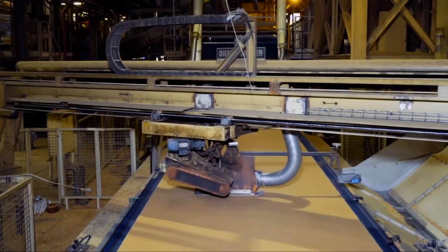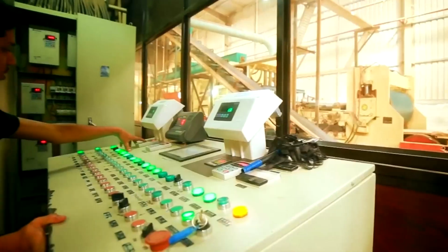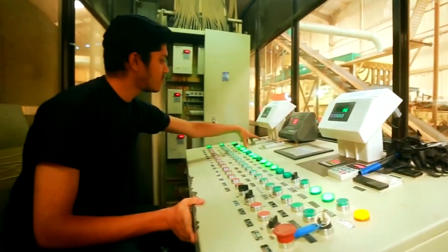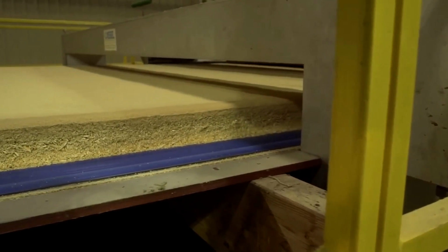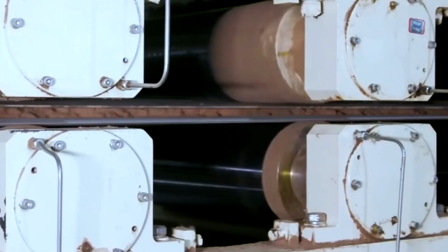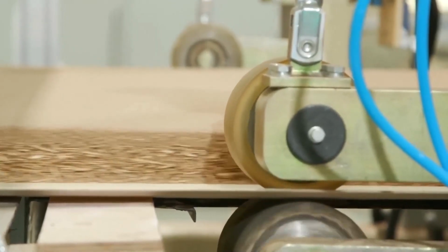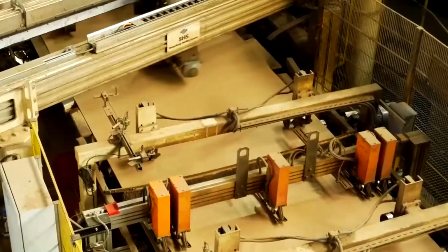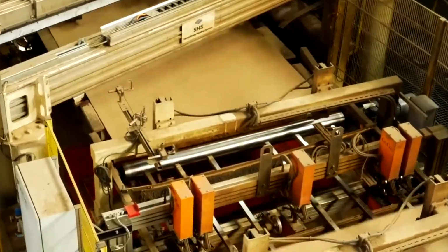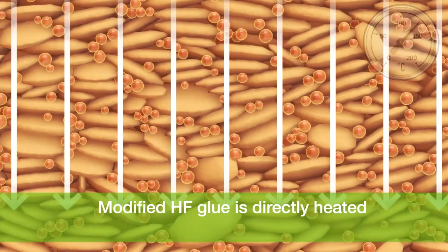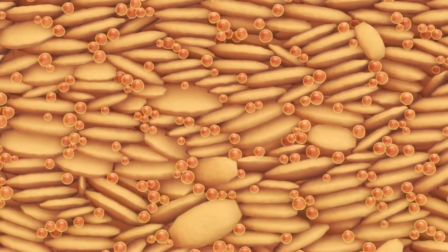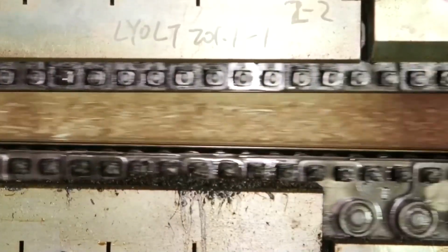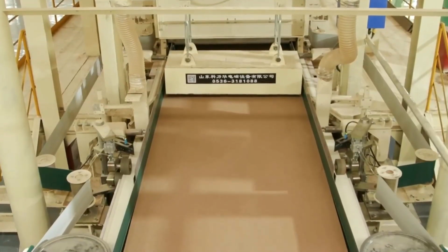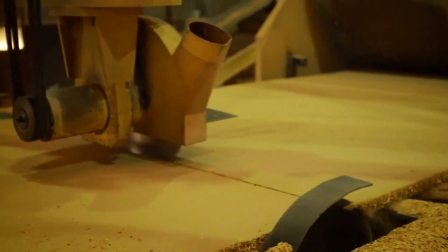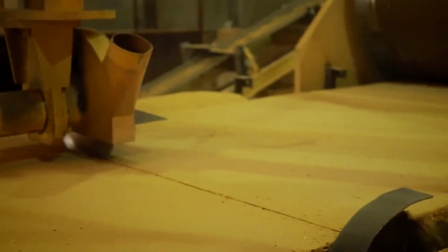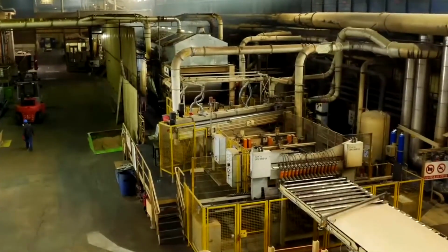Temperatures soar to between 280 and 430 degrees Fahrenheit, while pressure climbs as high as 600 pounds per square inch. For 2 to 6 minutes, the mat endures this extreme environment, its duration dictated by the board's specific type and thickness. Within this crucible, the resin undergoes a profound change, transitioning from a liquid into a solid state to form a network of durable bonds, locking the compressed wood particles together.